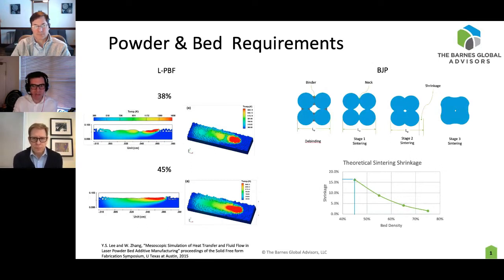Do we have just a delamination effect? In this case, do we have a poor adhesion between our layers because our binder didn't quite make it all the way through? Are we blowing away the powder, like you said, in the ballistic case? So there are things that it depends on. It really depends on how well tuned your process and your inputs are, both types of feedstock, powder and binder, and then how well you can adjust for those through subsequent steps of the process with respect to the debind and sintering stage. And then ultimately, how does that come out to be your shrinkage factor? Can you adjust or control for that as best as possible through all the post-processing steps? So it really does depend.